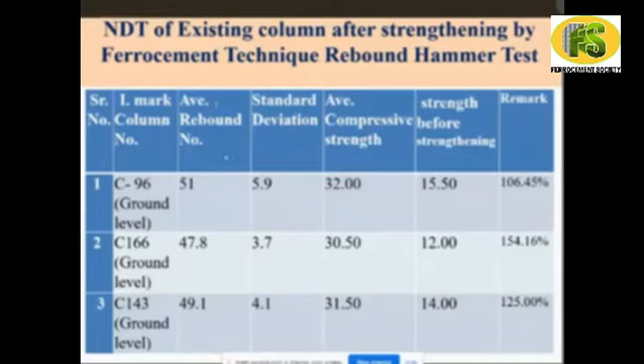I can show. Okay. So this is the average compressive strength. This is the detail, that means the rebound number 51 for column number 96 at ground level. Average compressive strength is 32, and here is the strength before strengthening. These are the strengths after strengthening. That means after using the ferrocement technique, we have achieved 32 MPa. And this is the strength before strengthening, 15.50. That means around 106.45% enhancement in the strength.